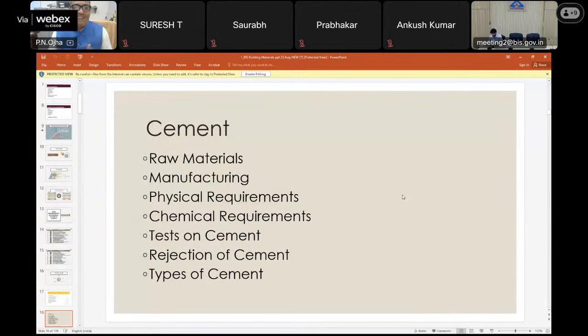So the raw material of cement is mostly limestone, and some additives can be added like laterite and all that. So calcareous and argillaceous materials are added. To remember it, limestone and other additives like clay, because cement is manufactured by having chemical compositions of oxides: lime, alumina, silica, and iron. Lime means CaO, alumina means Al2O3, and iron oxide means Fe2O3. So the material should have these oxides, and for cement manufacturing, these values are specified. Combined together, those materials are ground together into a powder-like material.